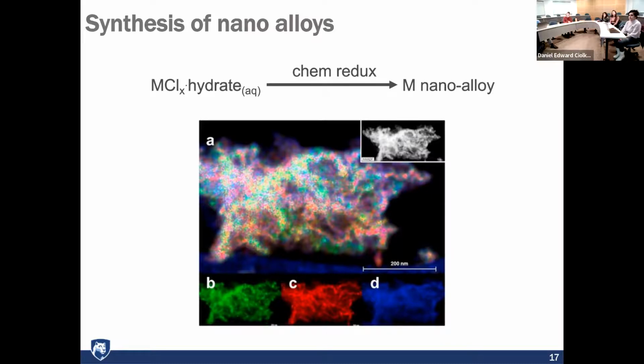And so here we have a transmission electron micrograph, a TEM picture of one of the catalyst nanoparticles. You can see there's a scale bar here. This is 200 nanometers. So we look at the catalyst, and the colors are indicative of where the different elements are. And I think green was probably iron, and blue was nickel, and red was oxygen. I don't remember what the colors were, but the take home message is that you don't see any areas where the colors are concentrated, right? The colors are spread out among the material, meaning that the elements are all evenly spaced in the material.